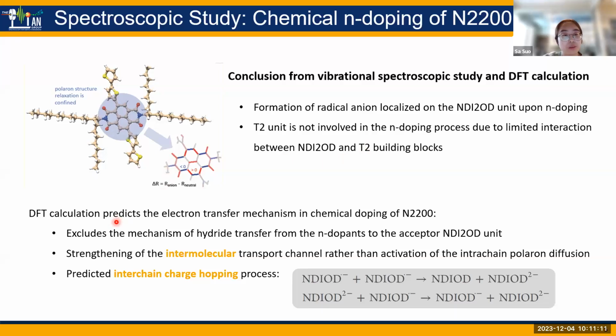Meanwhile, they also hypothesized something else from the DFT calculation. The fact that their radical anion simulation from DFT calculation aligns with what they observed basically excludes the mechanism of hydride transfer from the dopants to the NDI-2OD unit. And because they see the confinement of the polaron just localized on the NDI-2OD unit, they strengthen the intermolecular or interchain charge transport channel instead of the intrachain polaron diffusion.